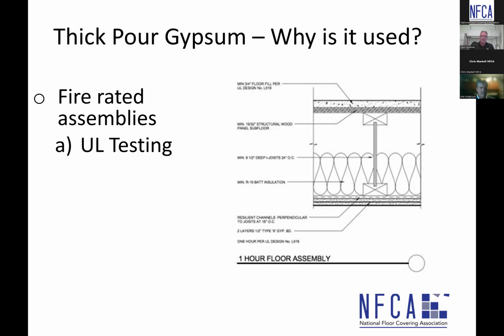Yeah, so you don't get skim coat gypsum material. Not these types of products, which are basically gypsum in a bag where we add sand at the site and add water at the site. There are engineered self-leveling underlayments, which we'll talk about in a future slide, that have a lot of powdered polymers in there to increase performance, enabling those products to be poured in thinner applications, 1/8 inch, 1/4 inch, feathered edge at transitions. But traditional gypsums are referred to as thick pour because it's a minimum 3/4 of an inch, and they're commonly poured an inch, 1.5 inches, and sometimes deeper.